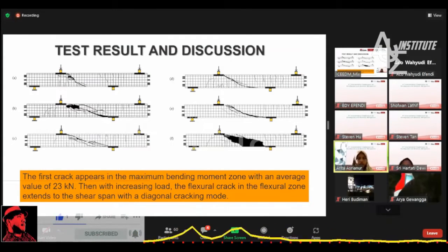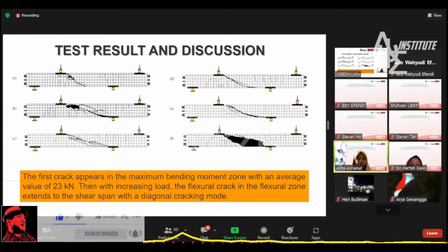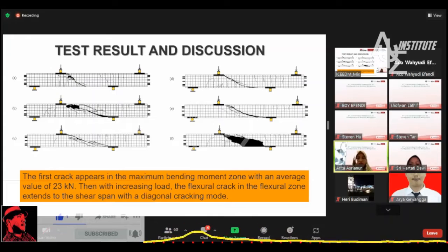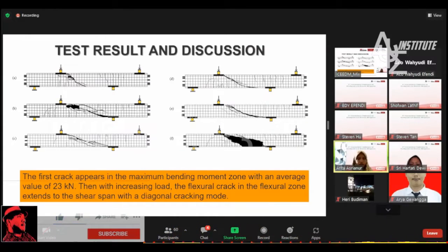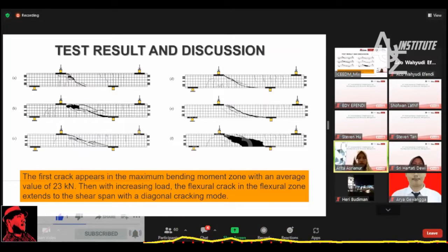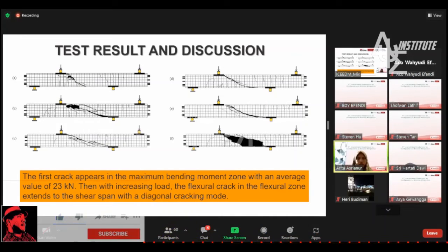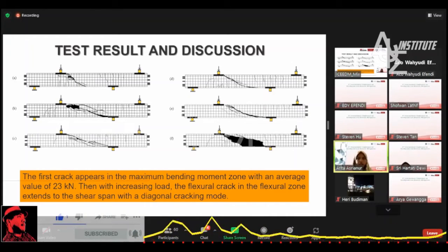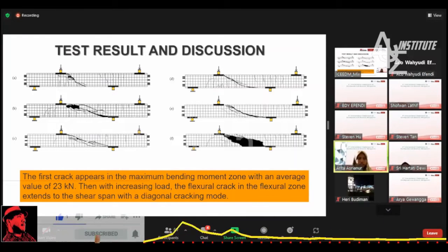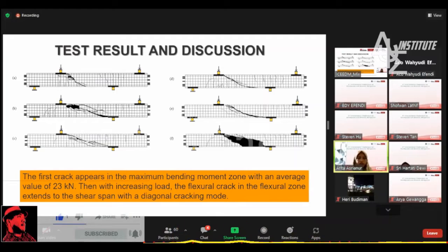From the test result, it can be reported that the first crack appears in the maximum bending moment zone with an average value of 23 kilonewton. Then, with increasing load, the flexural crack in the flexural zone extends to the shear span with a diagonal cracking mode. These figures show the crack pattern of the specimens, and it's shown that all of the specimens failed in shear with wide diagonal cracks, as predicted in this study.